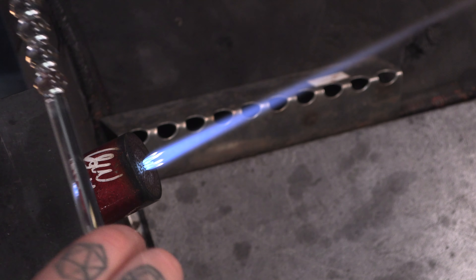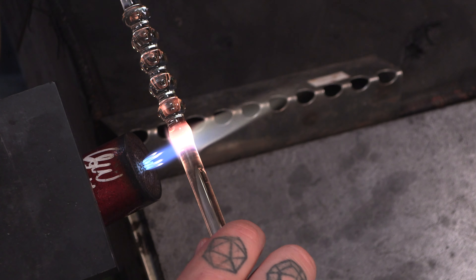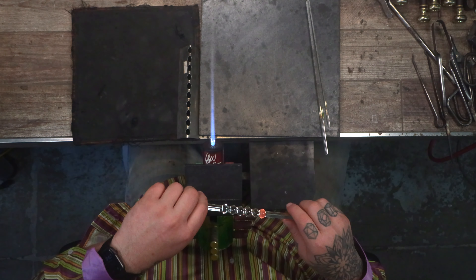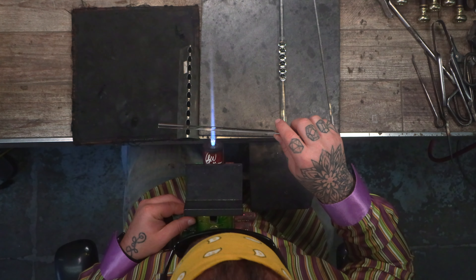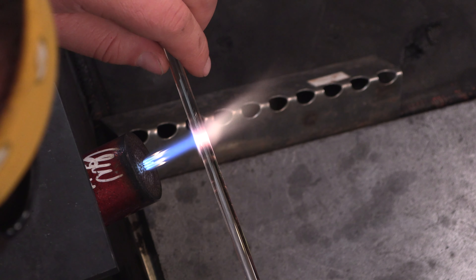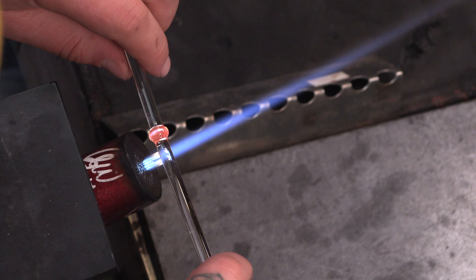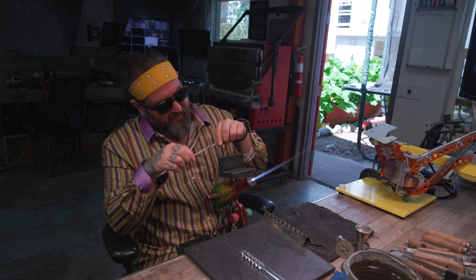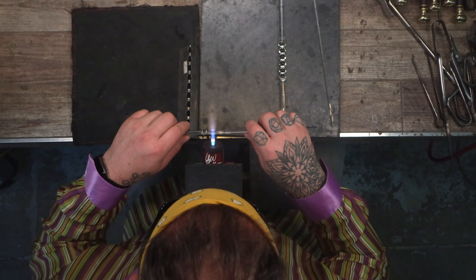You do want to imagine there is a small string or alignment all the way through. If you can keep these centered, each one progressively will be easier and easier. I'm just heating it up and then pushing just a little bit, rocking back and forth, letting it cool. Now that I have the 10 millimeter rod finished, I'm going to start working on the 7 millimeter one. I'm going to turn my flame down a little bit so I'm heating up less glass at once — heat it up, take it out of the flame just a little bit, and start to push and finish the shape completely outside of the flame.